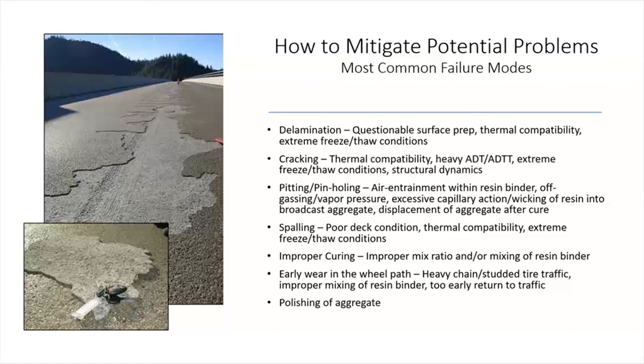And the overlay system, if it's done well, it's a good strong overlay, and it's going to pull up that weak area if possible over the years. And it's wanting to do that if the deck's not in good condition. You want to make sure the resin is mixed at the proper ratio and mixed for a long time. Like I said, if these guys were mixing in buckets, I would make sure that they were mixing at the proper ratio and that they were mixing it and they had a timer.